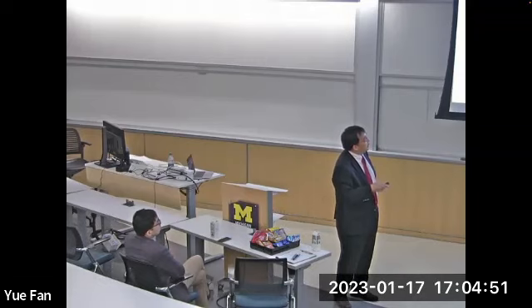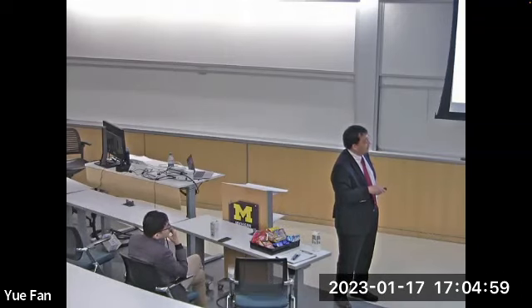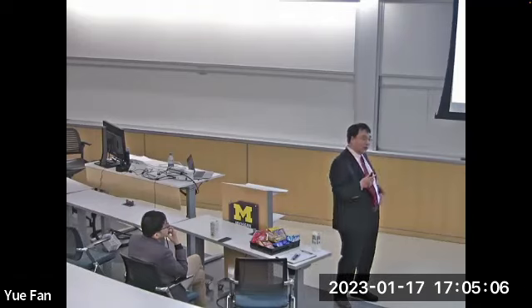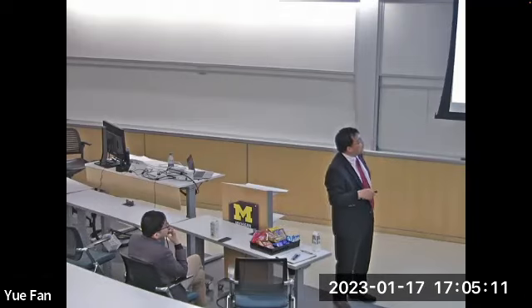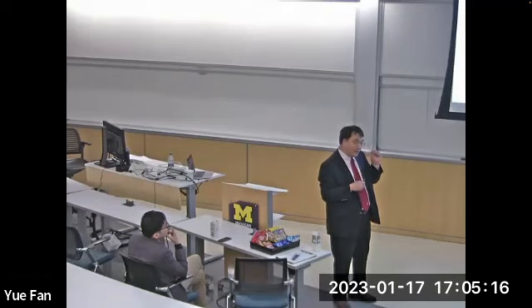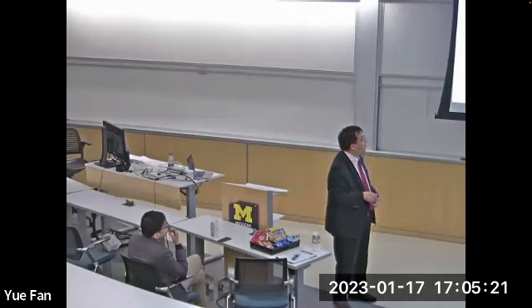And in this model, you can see that every time buckling happens, the plasticity in aluminum has a significant increase. Another one you will see after buckling in this model is a little bit of hardening behavior, due to this incompatibility. One has lower activity, another one has higher activity. But in the coarse model, you will see softening later. The softening happens with the buckling, and you trigger the plasticity in the aluminum copper. I will show that soon. And in the CP model, you will see very small buckling strain, but overall it shows a very quick softening process.